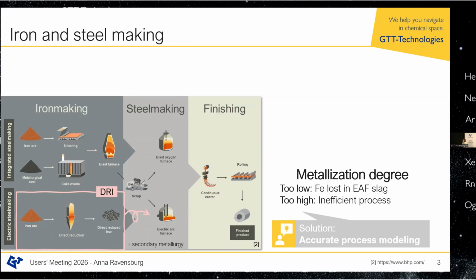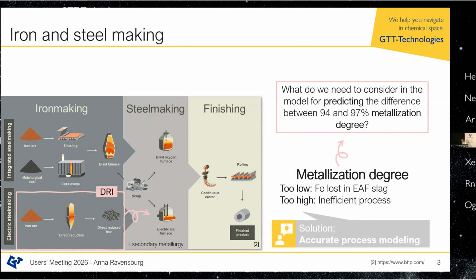Because you can see here, there's the DRI, and then the next step would be the electric arc furnace. It is really important what the metallization degree of your DRI is, so how much you have reduced your iron oxide to iron, before putting it into the EAF. If you have too low a metallization degree, then the iron that is still in oxide form is lost in the EAF slag. But if you have too high a metallization degree, you also have an inefficient process. What we're talking about here is not 60 or 40%. We are more in the range that Moritz already mentioned. They are very interested in whether it's 94 or 97%, for example. So this requires very accurate process modeling in order to distinguish 94 from 97.